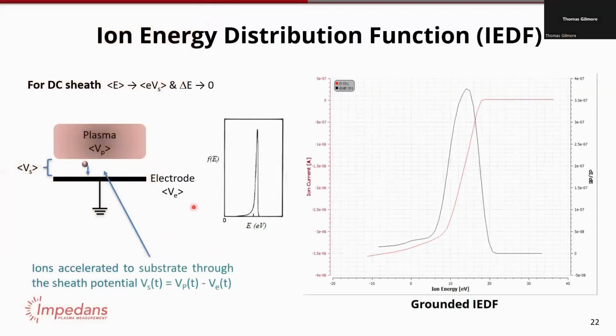For those of you who haven't seen ion energy measurements before, here's the simplest example where you have some plasma at plasma potential Vp. You have some electrode at an electrode potential, but let's assume that it's grounded, so it's zero. That means the ion energy, which is what it picks up as it crosses the sheath, is going to be the difference between the plasma potential and the electrode potential. So if it's a grounded situation, if the plasma potential is 20 volts, then the average ion energy is going to be about 20 eV. And if you have some DC bias applied, it's the same idea. It's just the difference between the two voltages that gives you information on the energy. Now there can be spread in the energy due to collisions and due to temperature and so on, but this is a typical ion energy distribution.